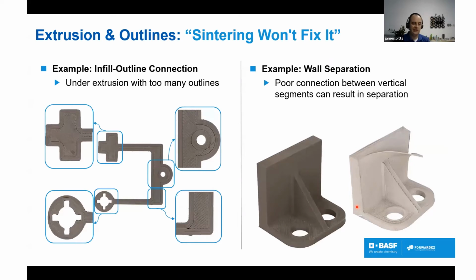And I'm gonna tell them, yeah, but those individual metal grains need to, the average distance at which they will connect is about the nominal diameter of a particle. So once you don't get density in your green part, those literally can't see each other and connect. The cheesy analogy I like to say, it's like you're trying to talk to somebody at a bar. You got to go over and be close to them to see if you can make a connection, right? Same way if they're far apart. Now, if we see these splits in the geometry right here, it's going to lead to situations where delamination and things like that. Again, thinking of the density tower, thinking about the other ones, these rules stack onto each other.